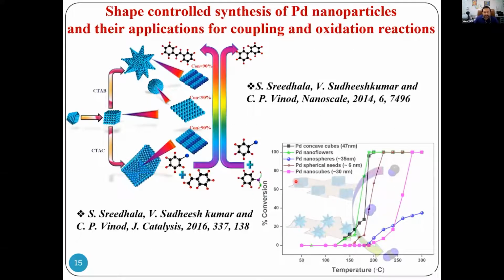Right. So once we have done with gold, we thought of looking at palladium. So palladium is also a very interesting system. You can also make such structured nanoparticles, wherein you can make a cube-shaped particle, which again is a low-index faceted nanoparticle. By changing the experimental condition, you can actually make a concave nanocube. When you make a concave nanocube, it again starts to show these undercoordinated sites on the surface.